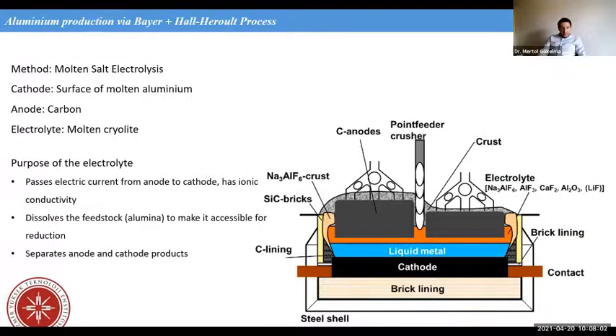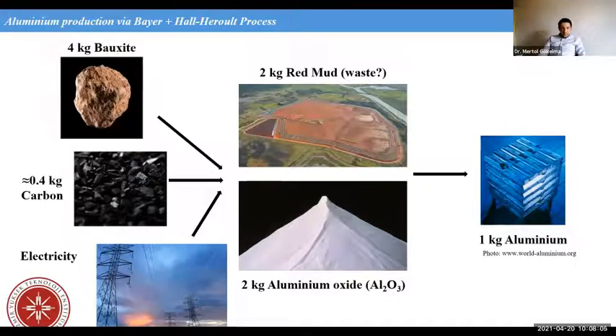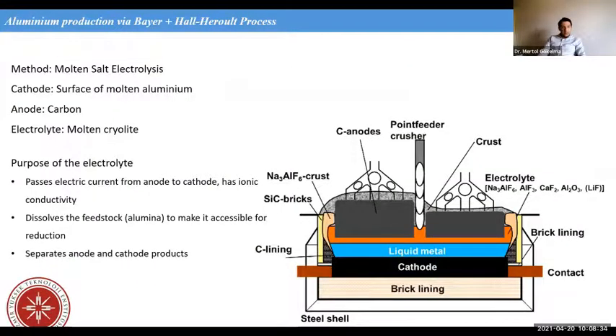And in the Bayer process, as you see here, this red mud is a muddy phase. This is the result of the hydrometallurgical processing in the Bayer process. By leaching, dissolving of oxides and precipitating, we produce aluminium oxide. So this is a hydrometallurgical process. That's why the waste of it is kind of a liquid mud phase. And after this, when we receive aluminium oxide from the Bayer process, then we go for molten salt electrolysis. The method in the Hall-Héroult process to produce aluminium is molten salt electrolysis.